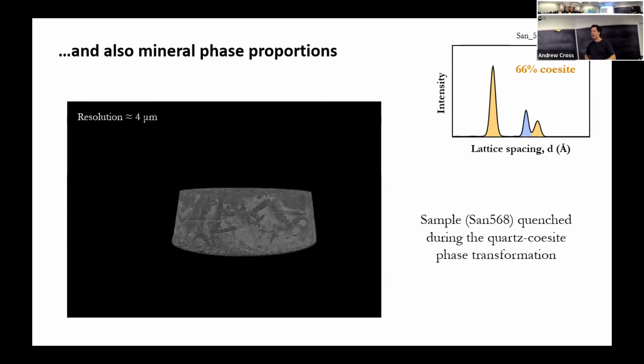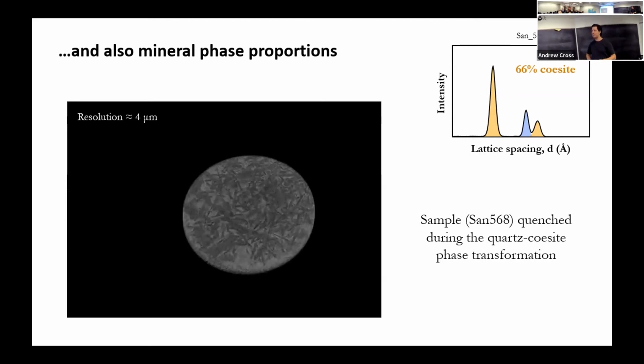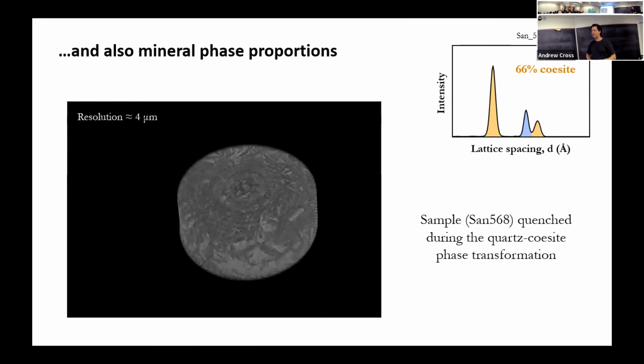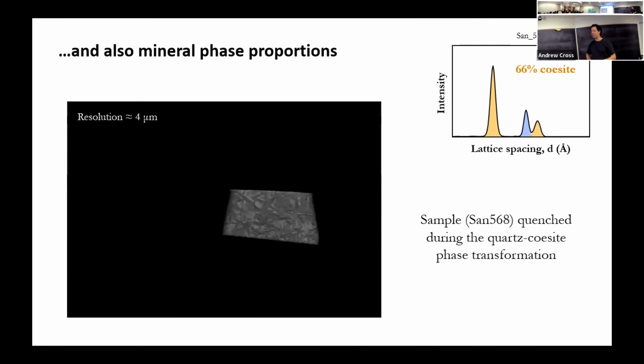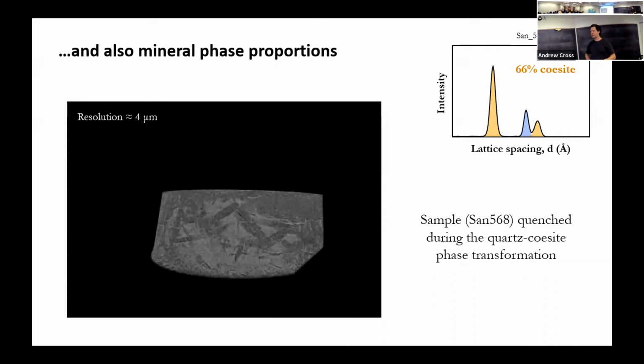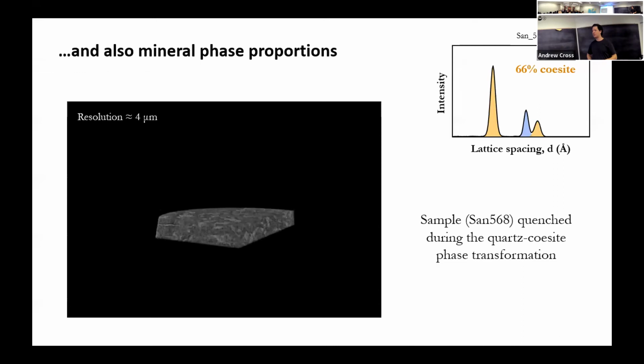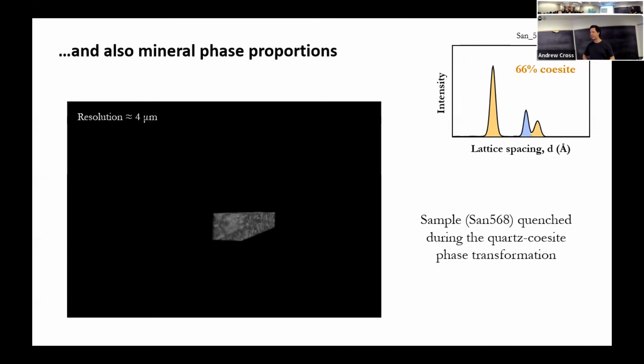And so what Rheoli's been doing with Veronique Leroux at Woods Hole is doing CT scans of the samples when they come out. And in the CT scans, you can see the darker, denser material is the Coesite, which forms these big tabular laths, these big needly things. So we can look at volume proportions for the entire sample, or we can cut it down to what we call the pencil, and this is the amount of material that's actually being sampled by our X-ray beam in the experiments. And so Rheoli's been working on quantifying volume proportions for a whole bunch of experiments where we've quenched midway through.